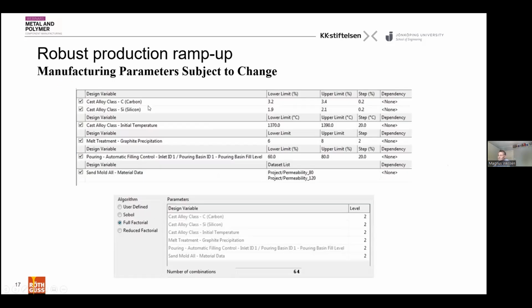So now, the matrix can get more ugly. I mean, we have the carbon content, which has an impact on the liquidus temperature, so that could affect the cold shot problems. The same with the silicon. And those things can vary, so then play around with that in 2 levels. Of course, also pouring temperature has a big impact for the cold flows. So that could vary as well. And then there's something called the graphite precipitation. I will not go into detail, but that's related to the shrinkage, we can say.